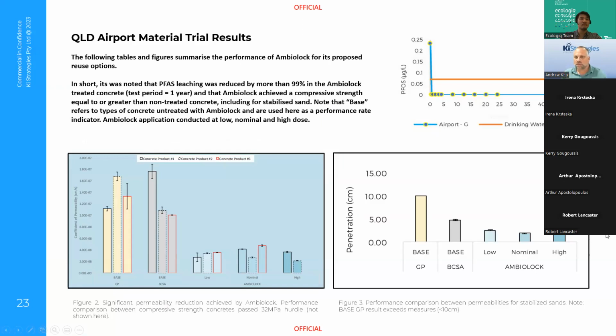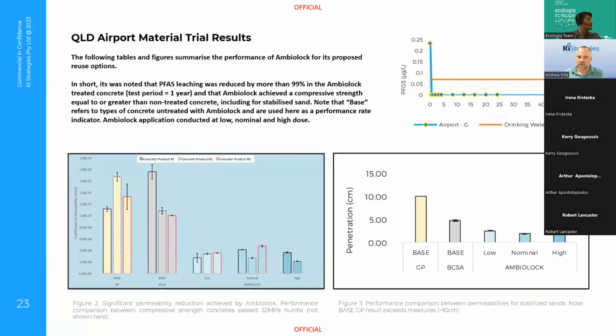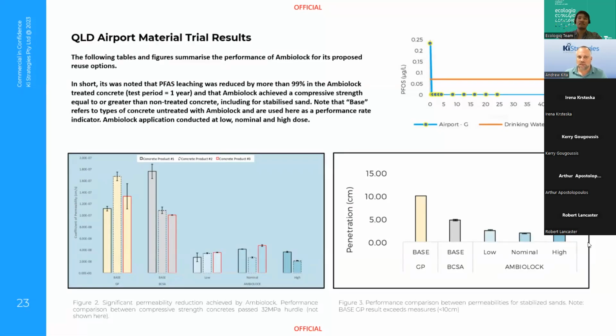The graph in the top right shows leaching of PFAS in particular, which is the most abundant fraction of PFAS that was present. And you can see initially the concentrations leaching were well above the guideline level we were trying to achieve, but within the space of a week, we had those leachable fractions down to the point where they were barely detectable, and beyond that, not detectable for a whole year of testing. So we were able to bind more than 99% of that PFAS into that stabilized sand matrix.